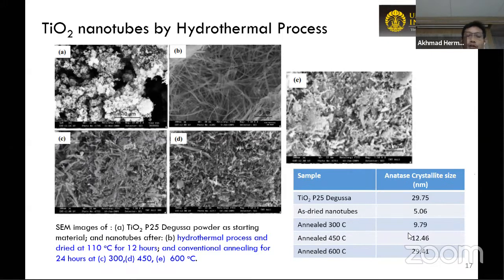But according to the X-ray diffraction, of course, we can estimate the crystallite size of the anatase by using the Scherrer formula. For the TiO2 P25 Degussa, of course, the crystallite size is quite large because it is the original one. And for the dried nanotube, the crystallite size of anatase is only 5 nanometers. It is expected because the phase is still amorphous and the anatase phase is still very little. That's why the crystallite size is only 5 nanometers.